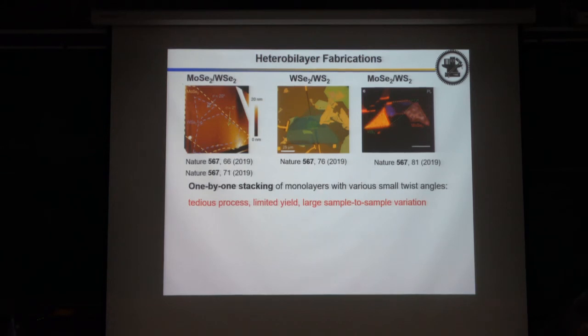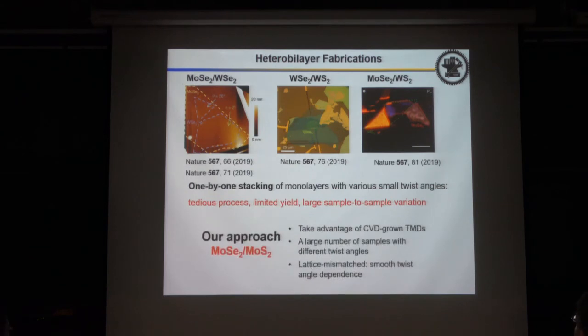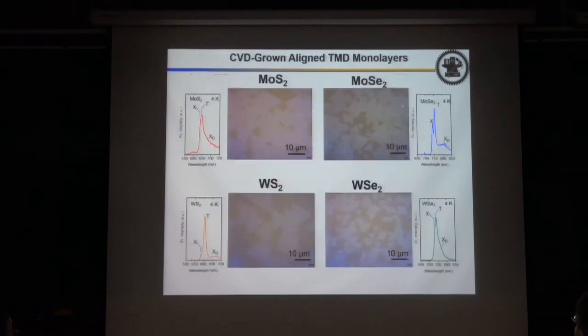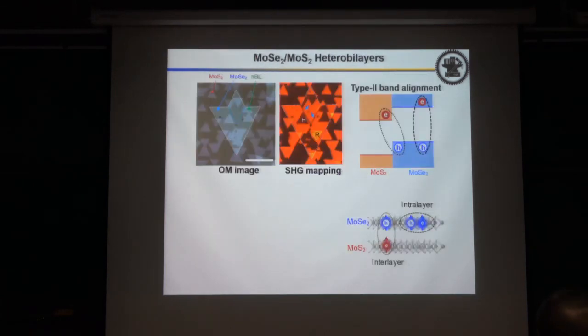So now we use another approach. Our approach takes advantage of CVD. For example, we grow highly aligned materials, and then we stack the two materials together. At the same time, we can use one larger flake to stack on another. So you can form many flakes with similar twist angle.